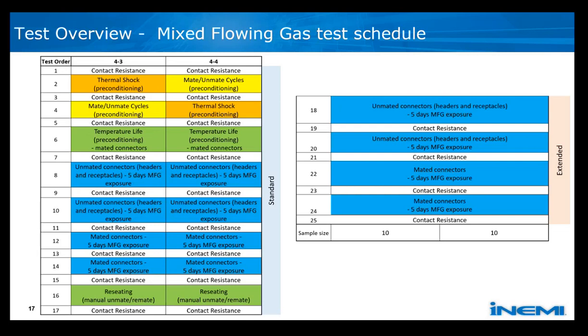And then the 10 days unmated, 10 days mated is performed in groups of 5 days. Then a resistance measurement, then another 5 days, then a resistance measurement, and so forth. Then a final reseating, which is, in this case, a physical mate and unmate. So that's very much a standard kind of test for qualification of connectors. The extended testing shown to the right is the concept of going through the 20-day MFG test a second time or a third time and even a fourth time if that was warranted to achieve the 70% failure rate.